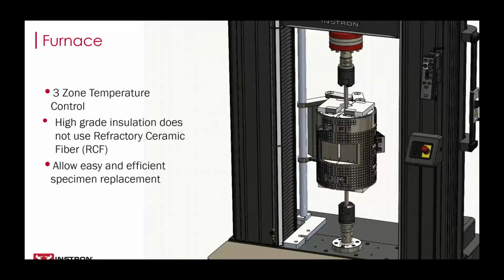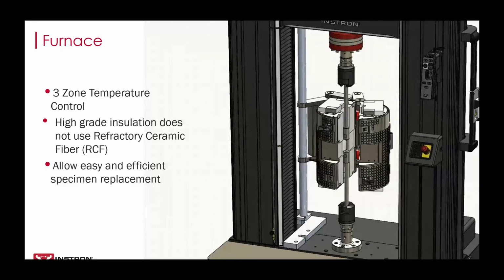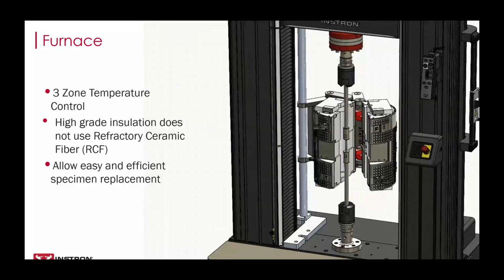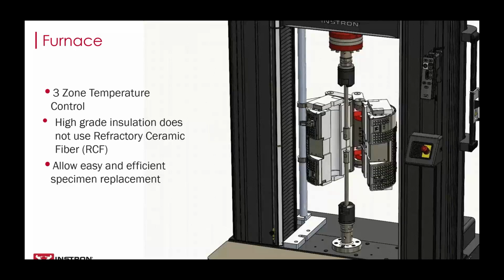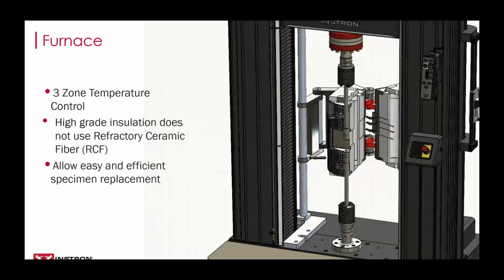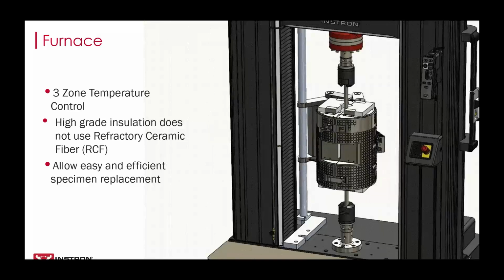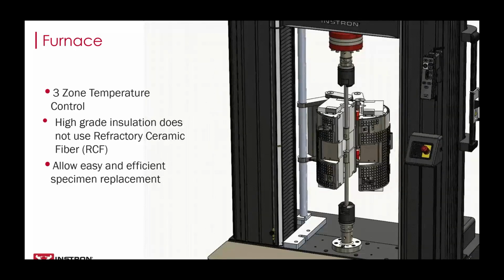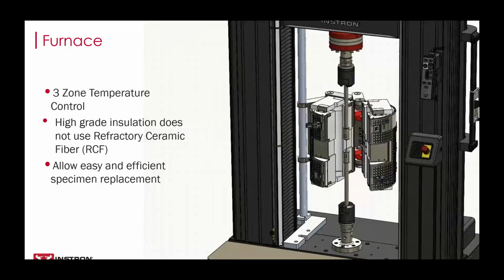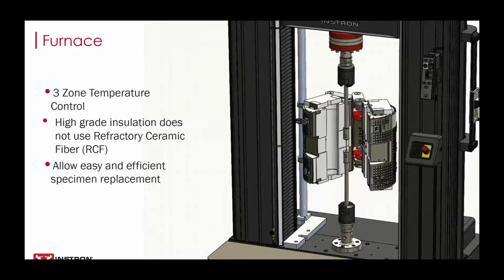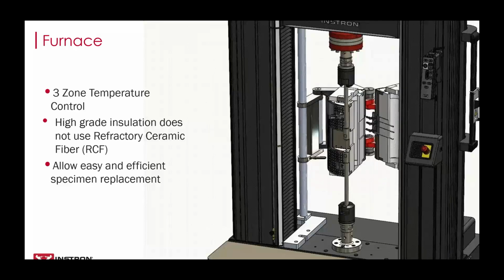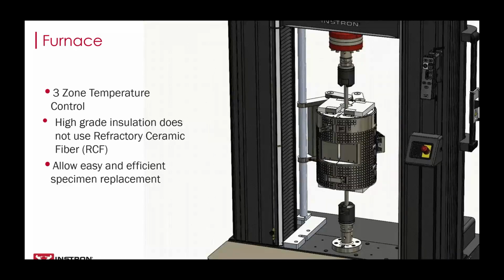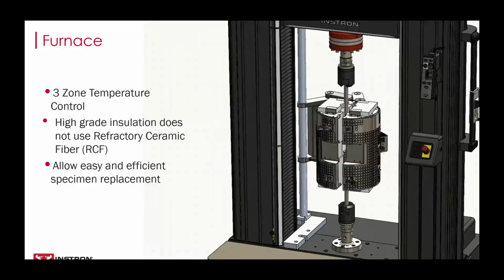These blocks can actually be slid inwards to hug the pull rods that enter and exit the furnace. This helps prevent any unnecessary heat loss during the test. Our high-grade ceramic insulation does not have the traditional RCF or refractory ceramic fiber, which can cause skin, eye, and respiratory problems with repeated exposure. The furnace itself sits on an adjustable mount that can be positioned to accommodate your specific system and load string. The mounting has a butterfly hinge, which allows you to easily swing the furnace in when it's needed for a high temperature test. And when the furnace is not being used, you can swing it out of the way, and that test space can actually be used for an ambient test setup. Next slide, please.